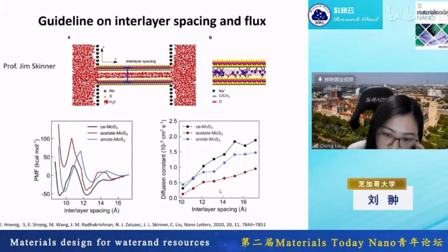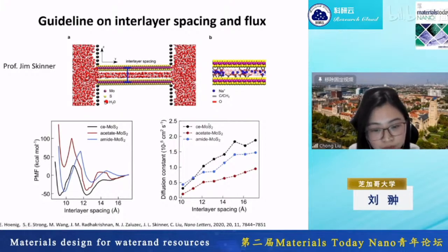And that shows you that, say, we look at this figure. We know that for the carbon nanotube case, a carbon surface doesn't carry any charge, and it has little interaction with the water molecule. For this case, we choose the acetate. It carries a negative charge. It does have a strong interaction with the water molecule. And in the simulation, it shows that it intrinsically has the slowest water transport property. But because its global energy well is at a two-layer water spacing, it does allow a higher diffusivity of water because the channel width is wider. So at the end, through this work, we developed a platform for us to continue studying water transport in the confined 2D channel as well as other small molecule separation.